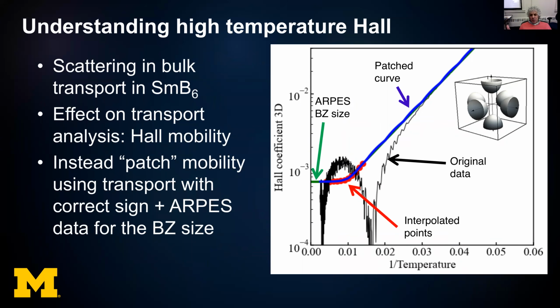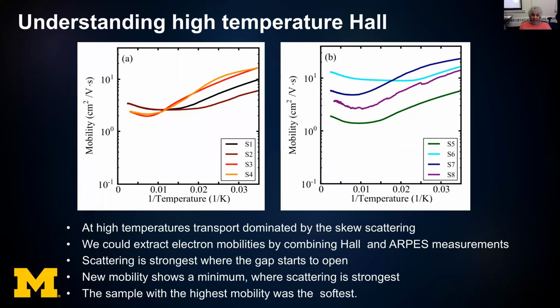So what we ended up doing, to get some measure of disorder or to see what the mobilities of the samples were, was to rely on ARPES measurements and extract some rough estimate for the Hall coefficient. And we knew the Hall coefficient is activated at low temperatures. By combining the 2, we said this would be a much more meaningful Hall coefficient. If we use such a patched Hall coefficient, then we could get some idea about the mobility of all these materials. And when we do that, we found the mobilities to be very low.